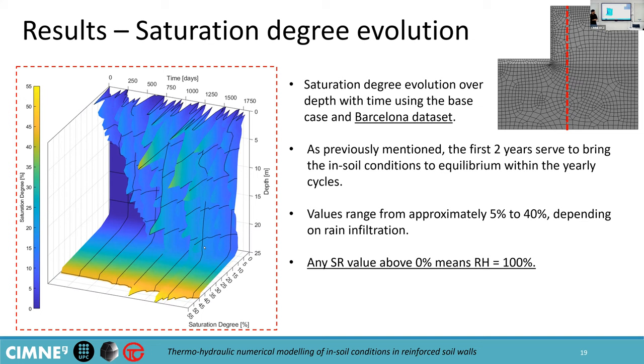Why are we emphasizing relative humidity so much? This is because polyester suffers from degradation due to hydrolysis — when the polyester fibers come in contact with water, they degrade. Most laboratory experiments are measured with in-air samples, meaning they are at a relative humidity of the exposed laboratory room, that's 60% or 70%. While in the soil, we have relative humidity values that could be up to 100% constant throughout the life of the system, meaning that laboratory conditions may not be representative of what the actual conditions are in the structure.